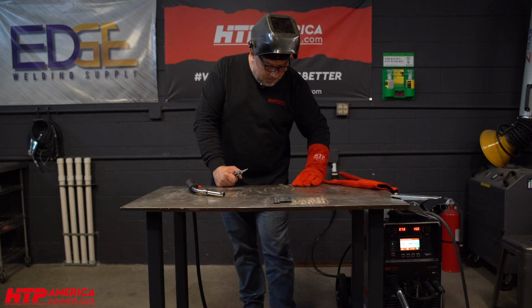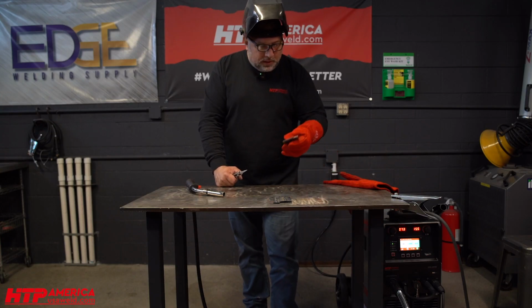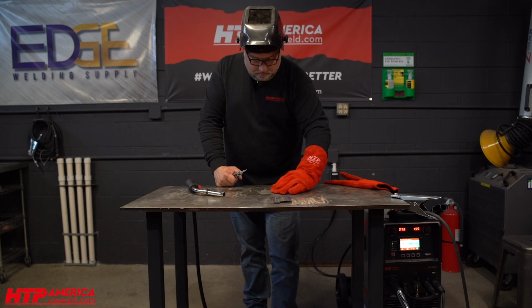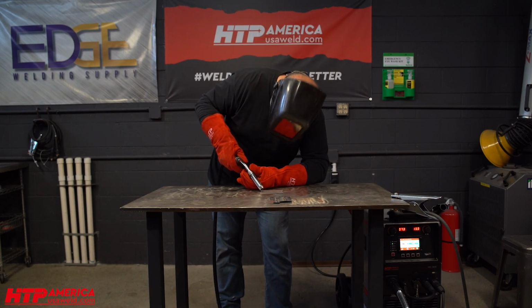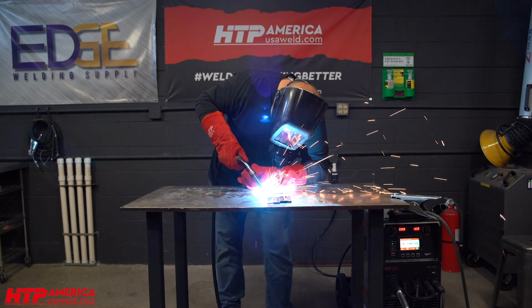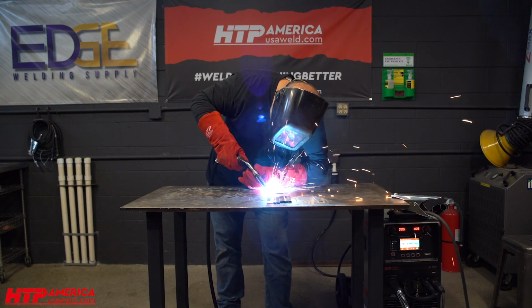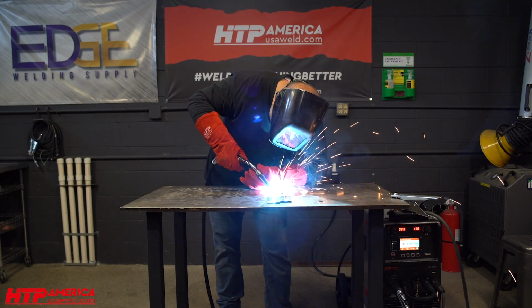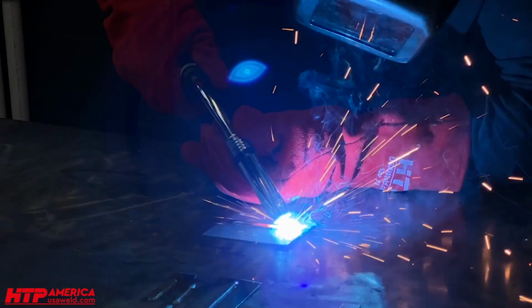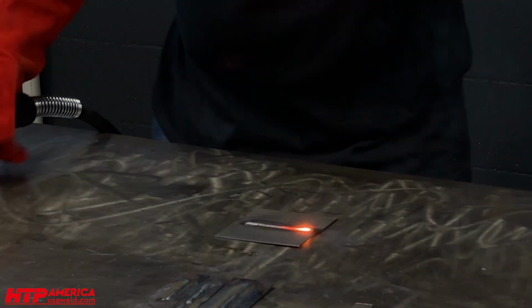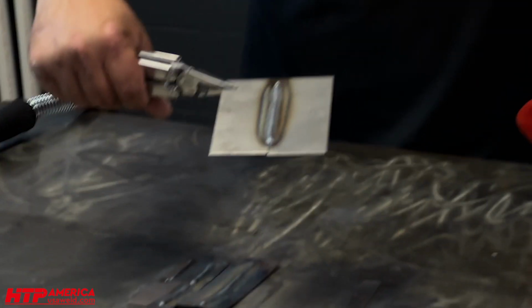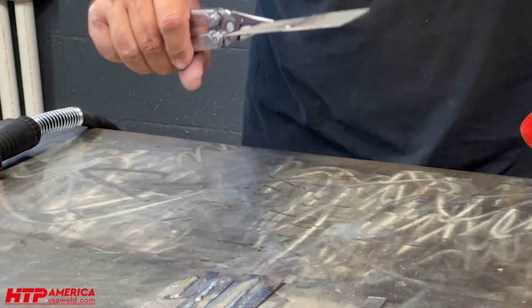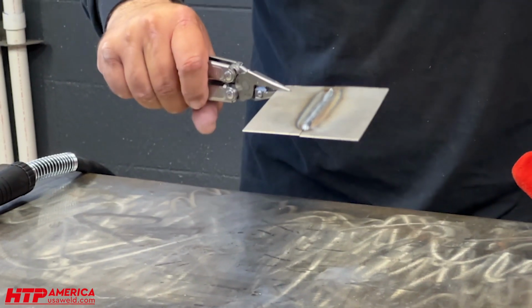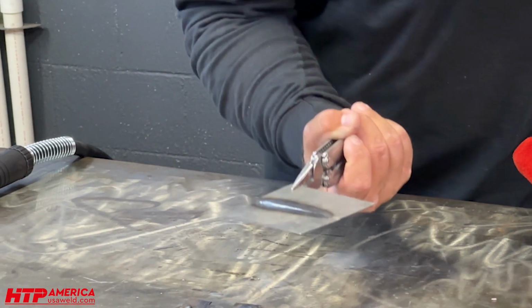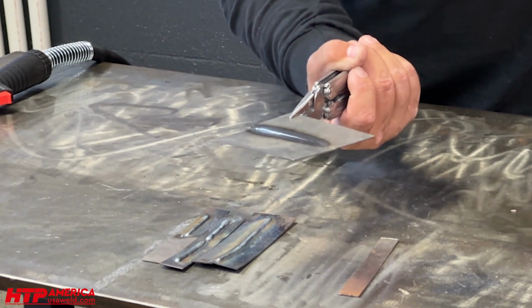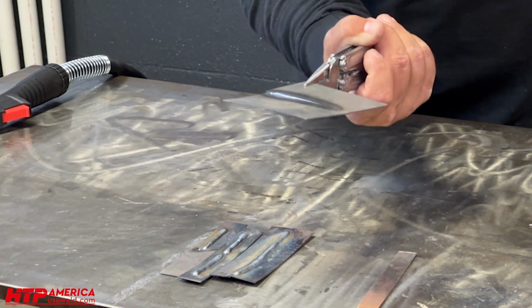So now let's bump it up. Let's weld a little bit thicker and see what it does. Nice narrow heat affected zone, narrow bluing zone. The bead lays down perfectly flat, nothing is crowned. You can see it came through just enough to get a full penetration weld without joint prep on this.